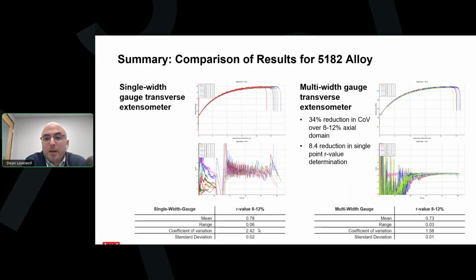And then so in summary, here's the side-by-side improvement going from a single width gauge measurement to a multi-width gauge measurement. The meaningful effect this has for the producer is that they can dial in their magnesium composition for improved strength while maintaining confidence that they'll get reliable, repeatable R values, compliant with the latest test standards. Now, I should note, although 5182 was the alloy of choice for this research, this approach is suitable for improving the reliability of formability characterization for any alloy exhibiting the Portevin-Le Chatelier effect, or the PLC effect.